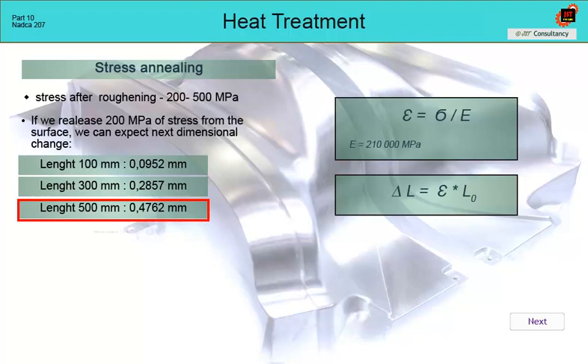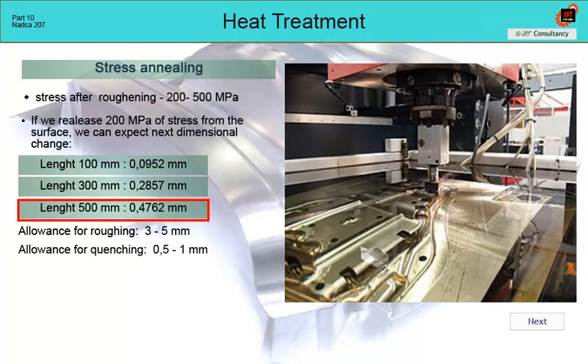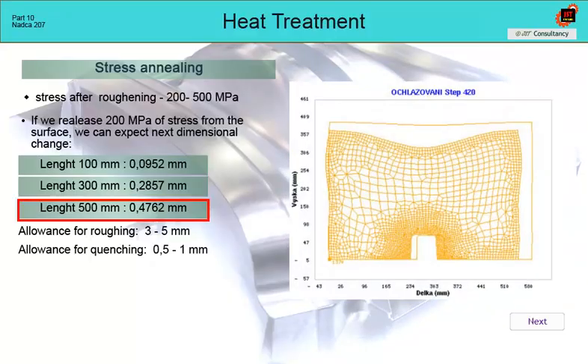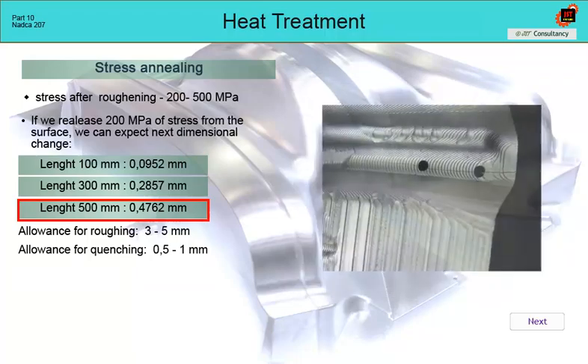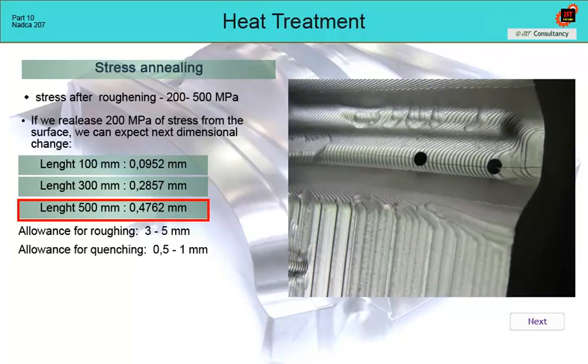We therefore recommend a roughing allowance of 3 to 5 millimeters for the insert itself. After stress annealing, we then machine the insert shape to give a final allowance of 0.5 to 1 millimeter for quenching. If we apply this procedure and the insert shows deformations after hardening, we can be sure that these are really only deformations from quenching, without any deformations from machining. At the same time, this finishing machining before hardening will allow us to prepare the quality of the insert surface for quenching without significant stress concentrators. But this depends on the skill of the machine tool technologist.